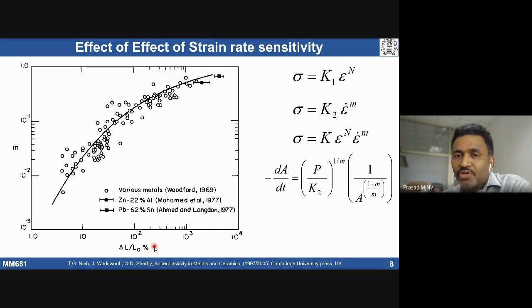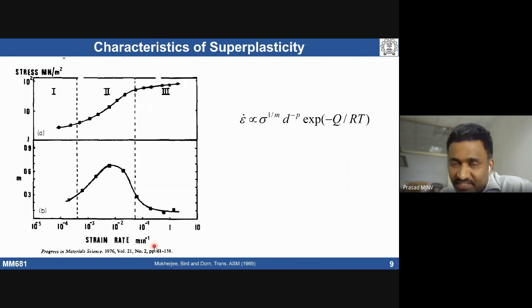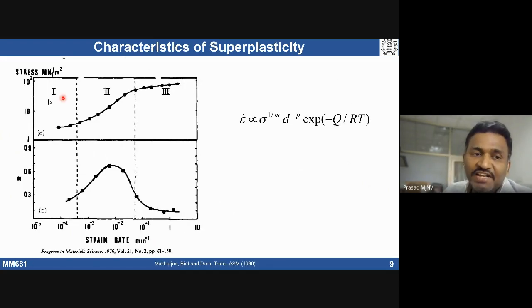So when we talk about superplasticity, it has some characteristic features. For example, if I deform a material under tensile loading conditions, we'll get a stress-strain curve at different temperatures and different strain rates. Now fix the strain and temperature, and see how stress varies as a function of strain rate. At a fixed strain, typically we take 20, 30, 100%, whatever.